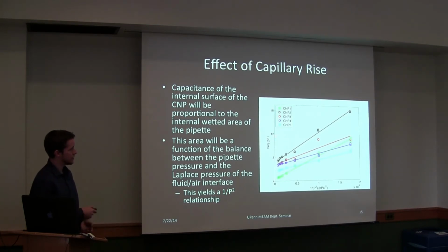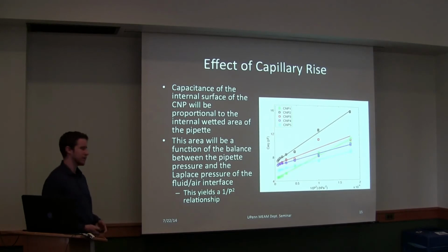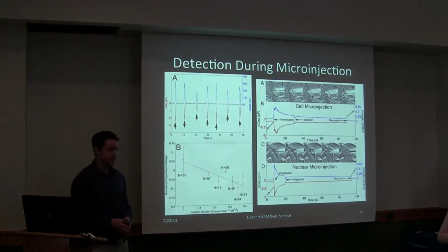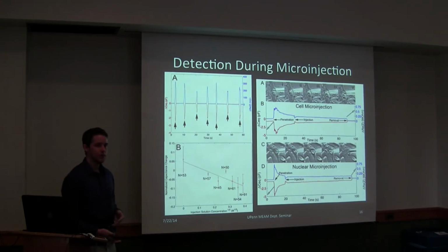And this plot here is just the equivalent capacitance versus 1 over p squared, showing that we do indeed recover a linear relationship and that we can accurately capture the behavior of the pipette at different pressures with different injection solutions in there.